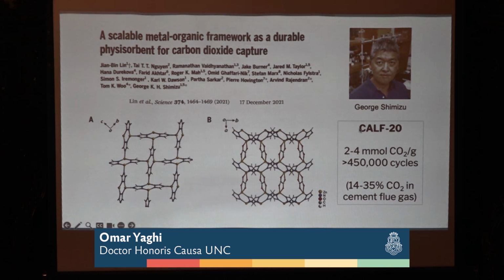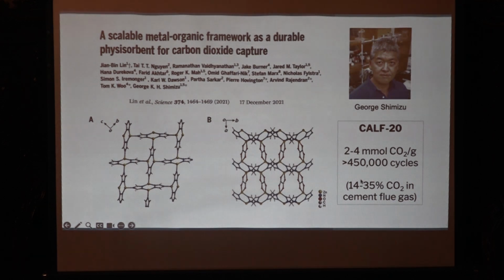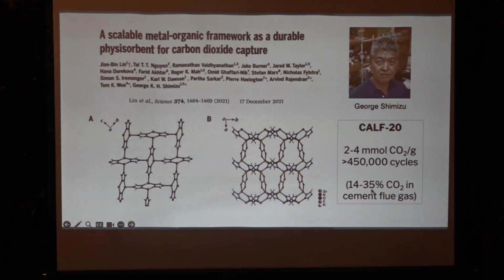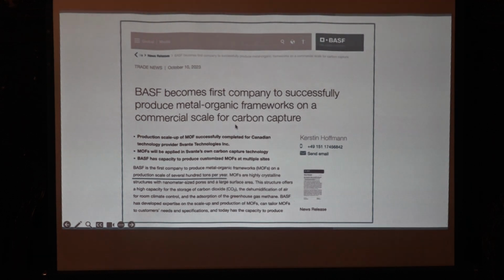So this MOF from one of my colleagues in Calgary, Canada, takes up 2 to 4 millimole of CO2 per gram at more than 450,000 cycles. This is already commercialized. This MOF will not work for air, but it will work for cement flue gas because it has higher CO2 amount. And already this is commercialized, and BASF last October came out with a news disclosure that they are scaling this up to hundreds of tons per year. Okay, so already MOFs are deployed in Canada, in cement plants, in several Canada plants to capture CO2 from flue gas.